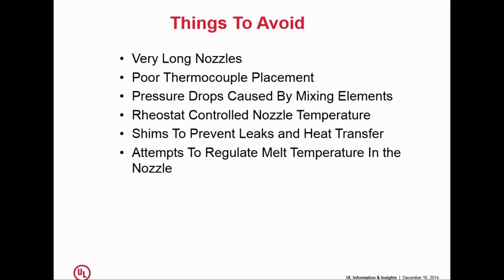If you put mixing elements in your nozzles, if you don't want to do the work of mixing properly in the screw, a lot of times people will put mixing elements in the nozzles. Those can work, but keep in mind many of those also produce a pressure drop, which makes the job of filling the mold that much more challenging.